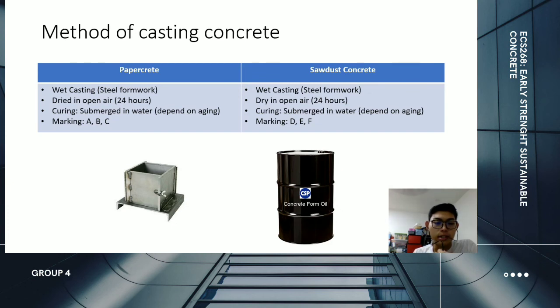Next point is drying in open air. After we have poured the wet papercrete mix into the steel formwork, we let it dry for 24 hours in open air, so there is great air circulation to help the papercrete dry. And after 24 hours, we open the steel formwork, and then we move on to the curing process, in which we submerge the papercrete cube in water, depending on how many days we want.